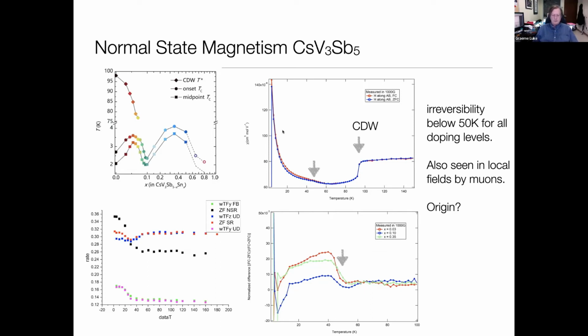So here's the susceptibility of one of our single crystals, for example. As you cool down, this is comparing both field cooled measurements in the red and zero field cooled measurements in the blue. And you see mostly that these measurements are exactly the same. And here's the charge density wave transition at 94 Kelvin. They're exactly the same. But if you look below 50 Kelvin, you start to develop irreversibility down here, that the susceptibility matters on how you got there. So there's something magnetic happening in the sample. We've looked, but it's not associated with the charge density wave transition.